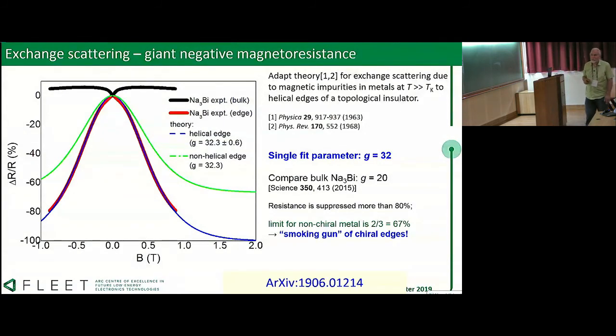Yeah. What's the resistance? Well, so the mean free path's about 500 nanometers, so that the resistance is h over e squared for 500 nanometers. But we have a millimeter, so the resistance is 1,000 h over e squared. And it's still length dependent? I don't know. Different lengths of the sample actually have resistances that seem to be different, and it seems to be that the sample's not completely homogeneous, which is not surprising that we grew this thing over a millimeter and it's only a nanometer thick. So I can't say that yet.